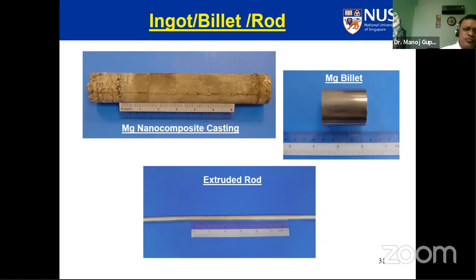Now, these facilities can melt up to 750 grams of magnesium alloy in one time, and you can run this twice a day, covering about 10,000 surgeries in a year. So you see how much we can cover just with a lab scale model here.